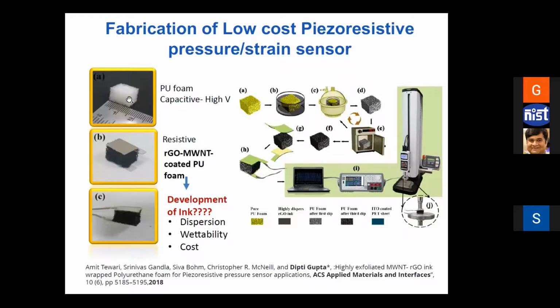Initially we tried to use it as a capacitive device, where you put 2 electrodes on 2 sides of it, and basically it's a porous material, so it serves as a dielectric with air filled in it. So when you press it, the air would be removed, its thickness would change and capacitance would change, and that's how it can work as a pressure sensor. But then this device was working at a very high voltage, so it was very power intensive. So we thought to convert it into a resistive device.